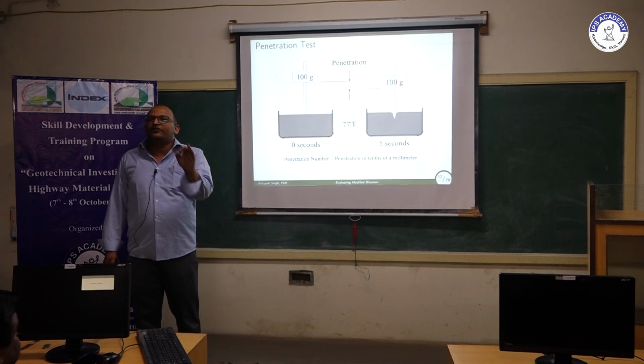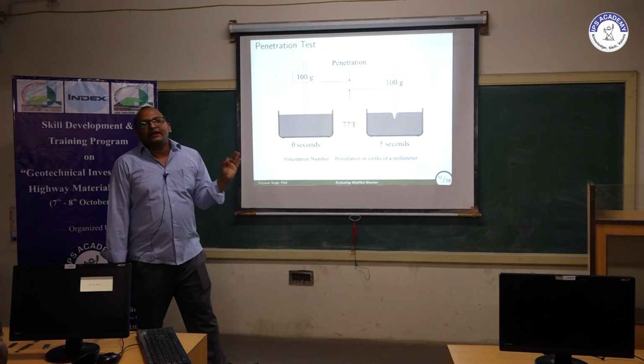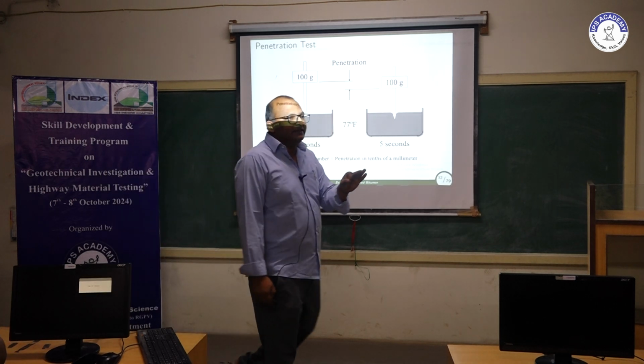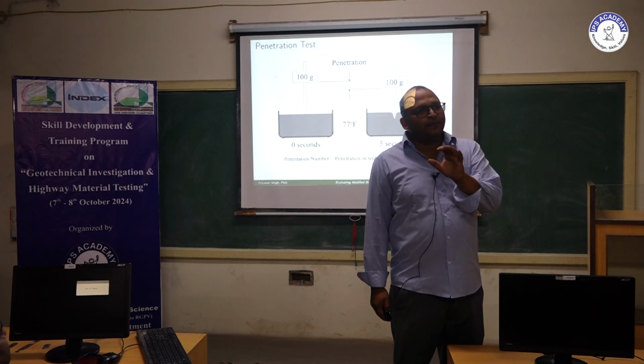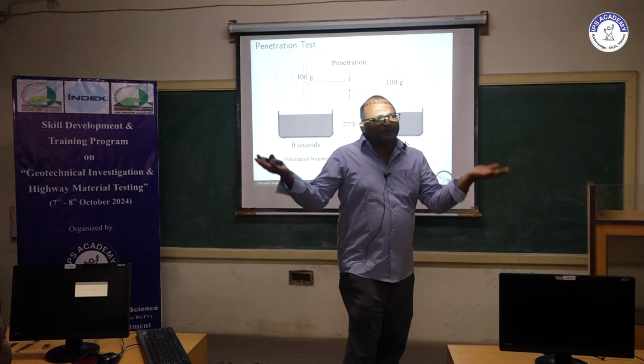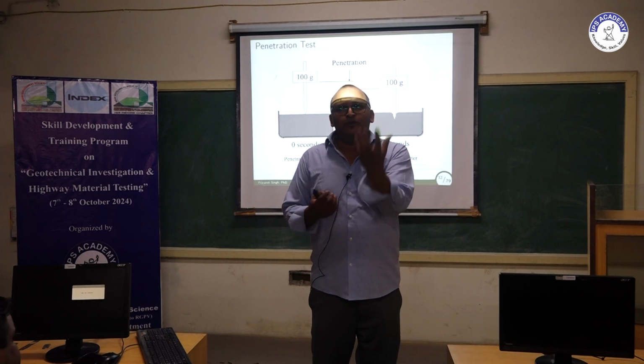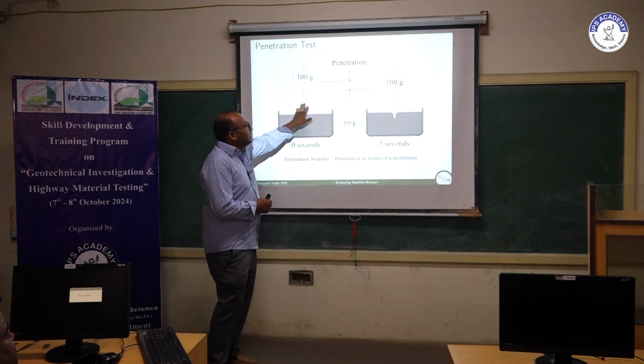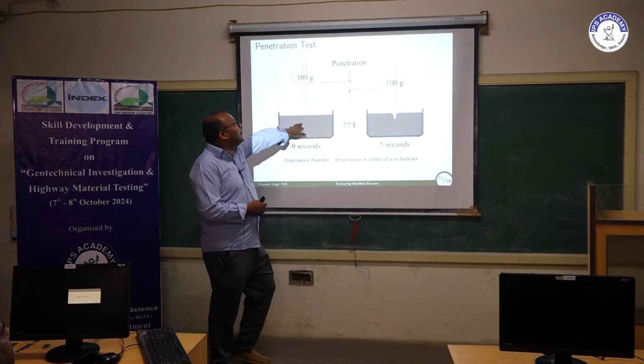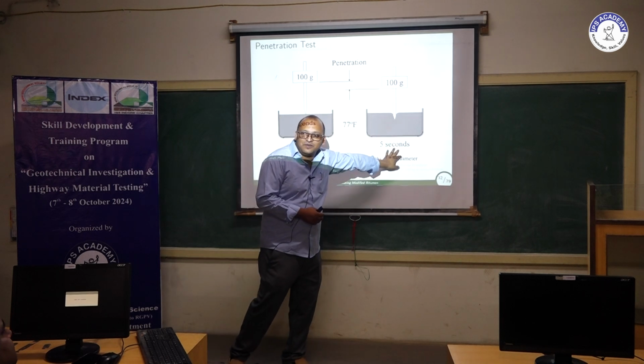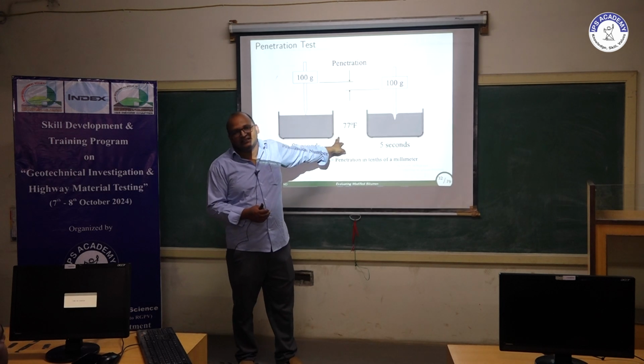So the first test we do to characterize the binder at ambient temperature, that means in the viscoelastic domain, is the penetration test. Very basic test. Today you might have performed the test. We will put binder in some container, and then we will take a needle. We will apply a 100-gram load for 5 seconds at 25 degrees Celsius. This is what penetration is.